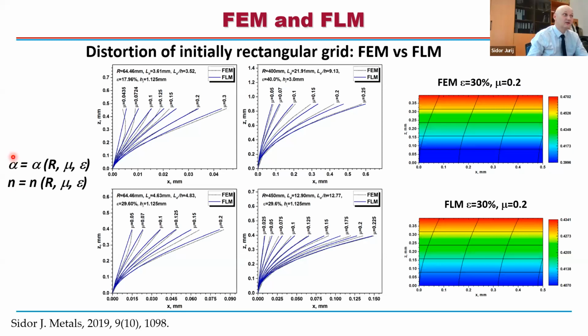In fact, it turned out that both of them are functions of the roll gap geometry. So R is the roll diameter, or radius, and mu is the friction coefficient, and epsilon is the degree of the deformation. So epsilon and R are parameters of the roll gap geometry, and mu is a friction coefficient. Okay, here you can see the results, for instance, of the 30% deformation.